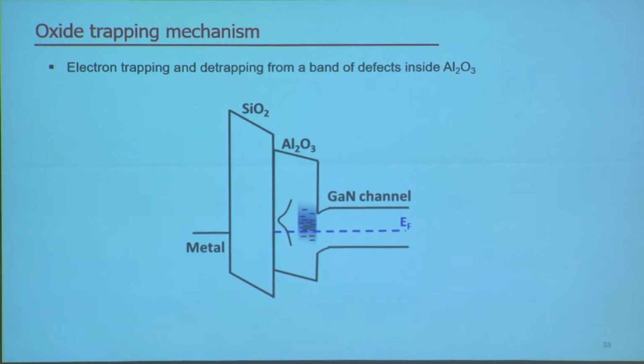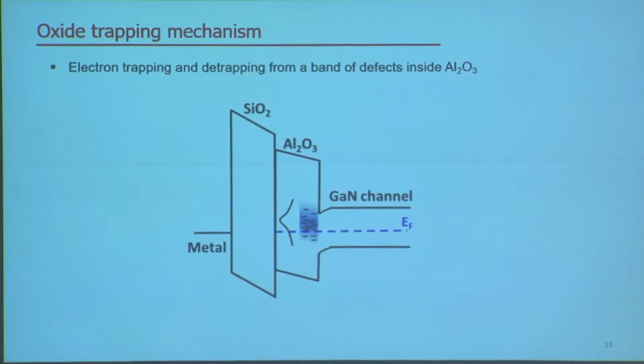So our study so far encouraged us to postulate the trapping mechanism for the first and third regime, which we believe is the oxide trapping and detrapping from one single band of defects within the aluminum oxide that are very, very close to the gallium nitride channel. So we believe that this defect band extends from below the Fermi level of the channel to beyond the conduction band of the gallium nitride channel. And the distribution of this band is probably following a Gaussian distribution.